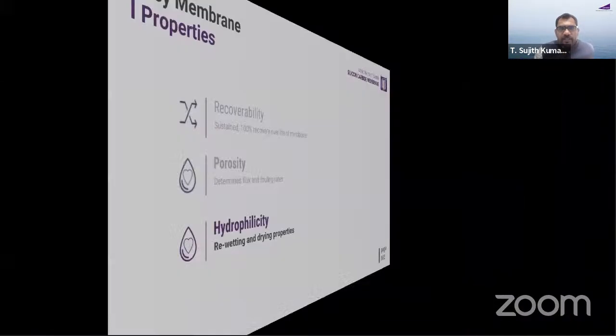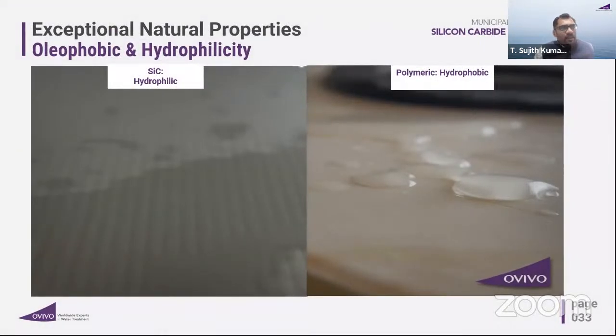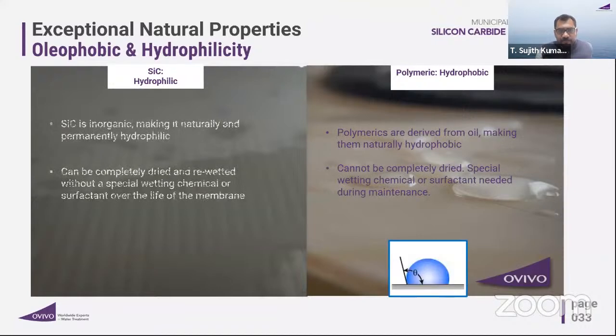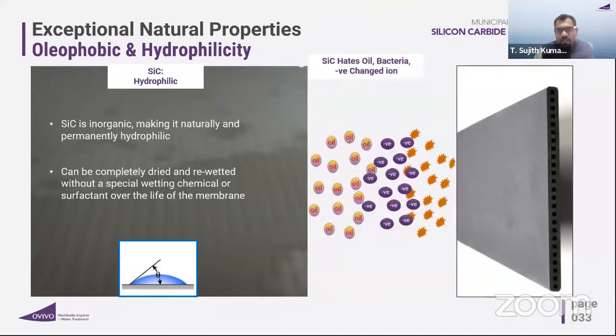And the hydrophilicity, these membranes are hydrophilic. It's water-loving membranes. It's also oleophobic. It repels oil. If you can see the picture, if you put a drop of water on the surface of the membrane, SiC silicon carbide membranes will immediately absorb that because it's water-loving. Whereas with polymeric membranes, if you put a drop of water on the surface, you'll see that it stays there because it repels water. It's because it's a hydrophobic membrane. And as I said, it's also oleophobic. It has also got negative charge. These membranes are also negatively charged.